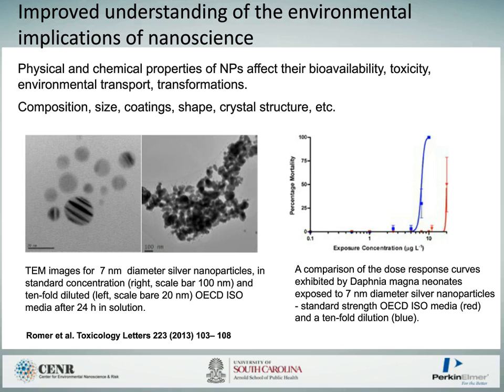But when we have it in the concentrated media and the particles aggregated, the dose-response curve is shifted to the right by an order of magnitude. So the aggregation of these particles into large aggregates of hundreds of nanometers changes the toxicity by about tenfold. So it's the same original material in a different form, and it has a huge effect on the toxicity.